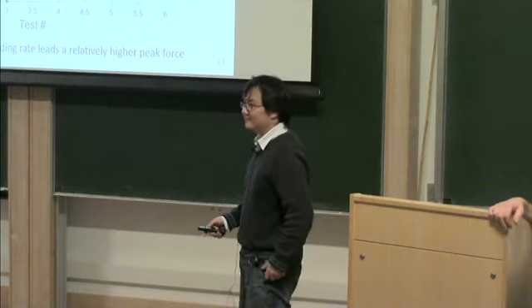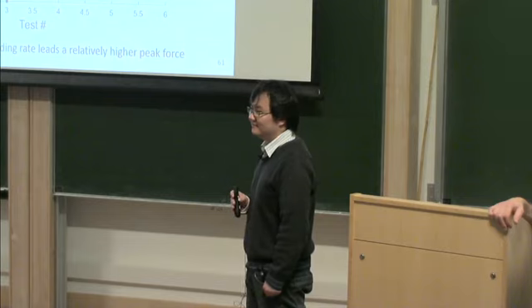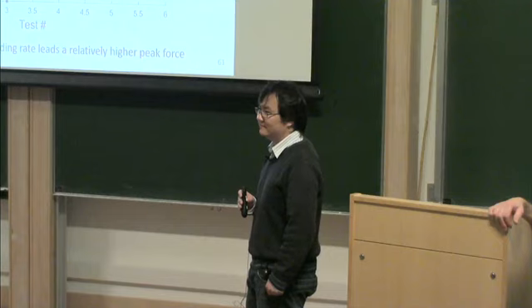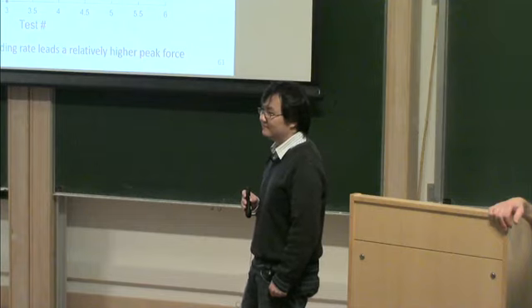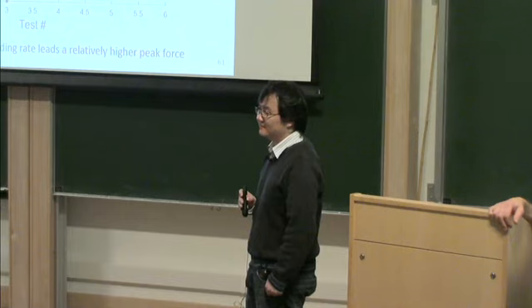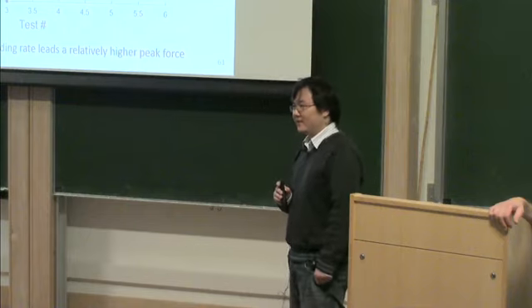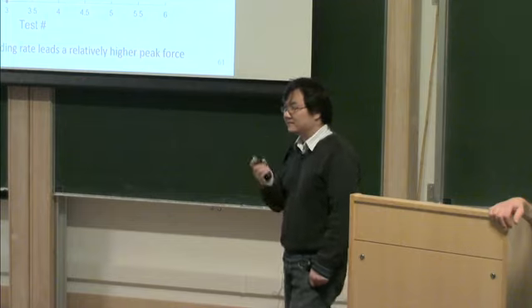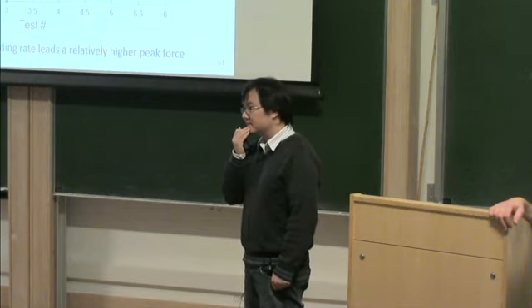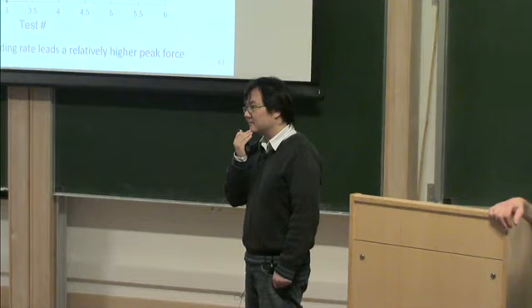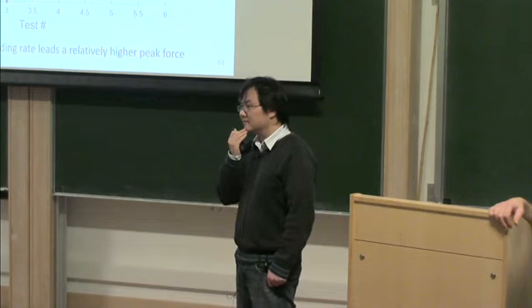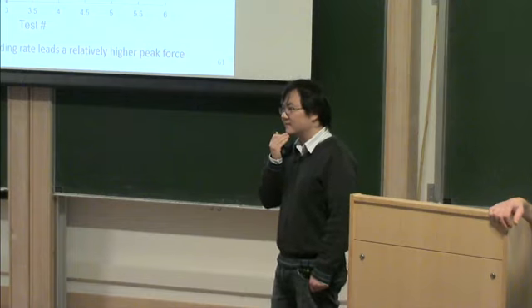Once again, about this loading rate effect, and in relation with Chris' comment, maybe could you try to quantify on your loading curve the deviation from linear elasticity on the loading part of the curve, and then try to correlate that with the peak stress? Because if you have another mechanism which is not elasticity, like creep or dislocation, plasticity, and so on, you should have something which deviates more from linear behavior. So you might try to quantify this.